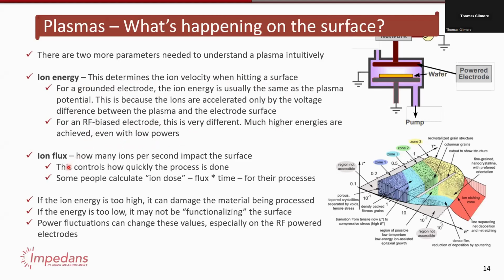And then ion flux is just how many ions per second hit the surface, so how quickly the process is done. It might be worth noting that some people care about ion dose, the flux times time for their processes. This is essentially to do with the thickness of whatever's being produced in the end. And as mentioned, the actual value of the energies matters. Too high, it can damage the material. Too low, it's not doing its job, functionalizing the surface or something. And in a typical chamber, power fluctuations, maybe the matchbox heating up or something like that, can change all these values mid-process. So it's not great.